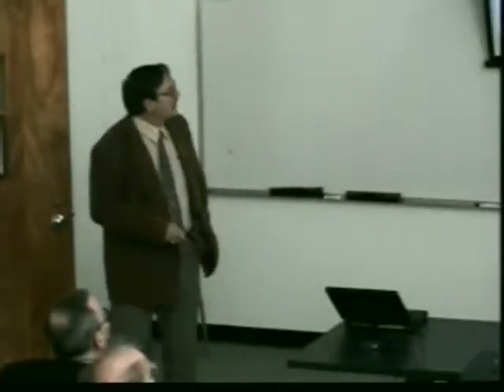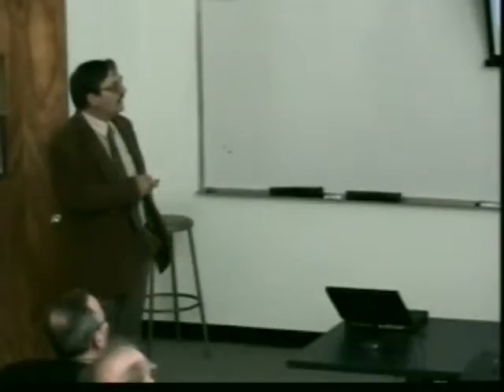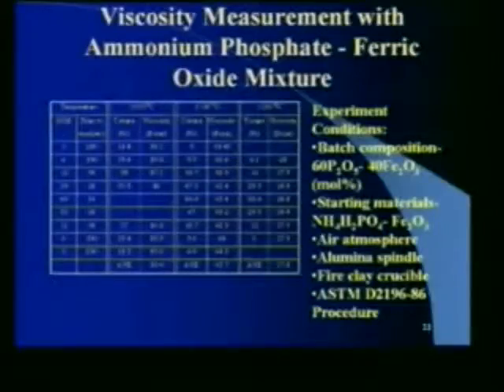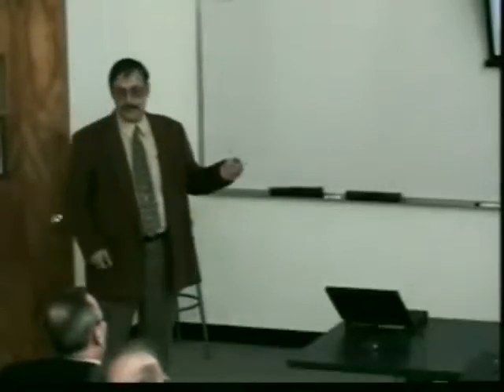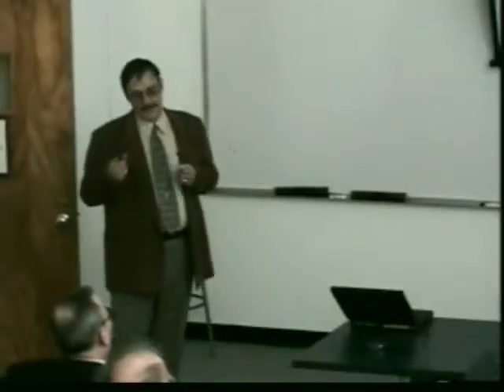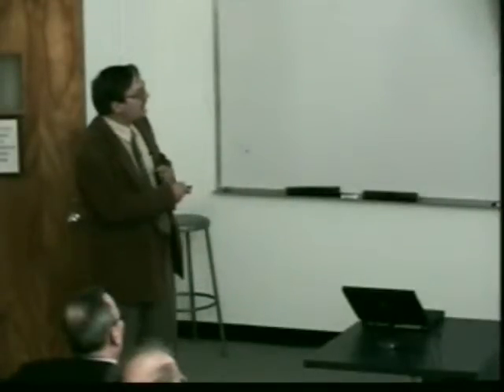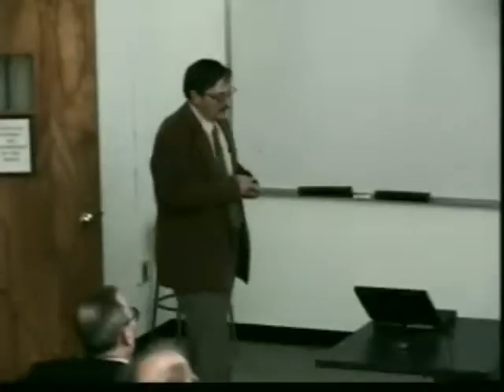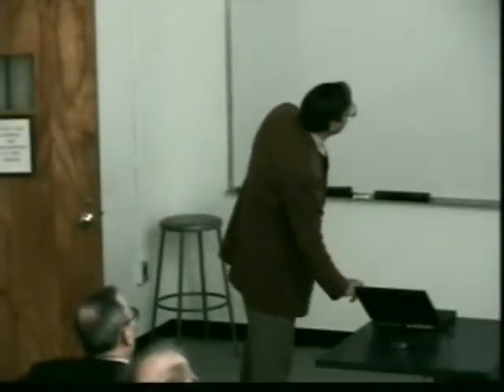Well, that's interesting, but if we start with ammonium phosphate and ferric oxide in the right proportions to make this 60% P2O5 and 40% Fe2O3, and you look at this, this is RPM and this is viscosity, and again, I'm sorry if you can't read it in the back. The light here is pretty low, but basically it is Newtonian. There's no difference in the viscosity versus shear in this system. So we have one system where we started with certain precursors that's non-Newtonian, and another system in which we started with ammonium phosphate and iron oxide, which is Newtonian, and we have to question whether there are some differences.